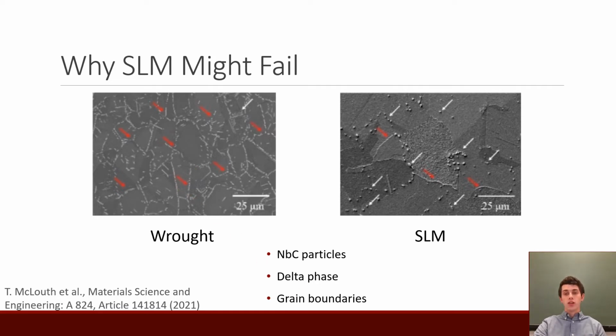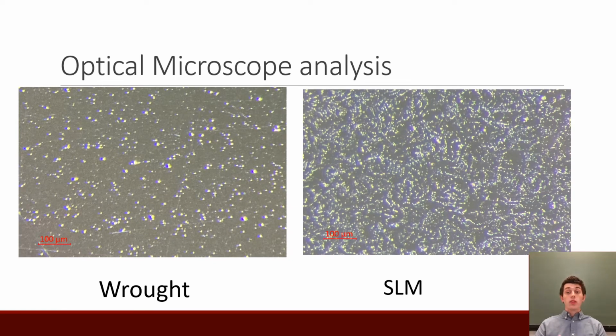Another important feature that has been seen in tests is that after tests, there are increased intergranular failure rates on the selective laser melted samples. So our goal is to confirm the presence of these features so that we can link them to the macroscale behavior in our samples. The analysis was undergone on an optical microscope on polished samples of both wrought and selective laser melted sample. As can be seen, each of these have a scale of about 100 micrometers.